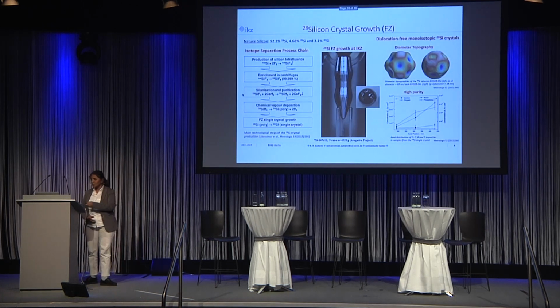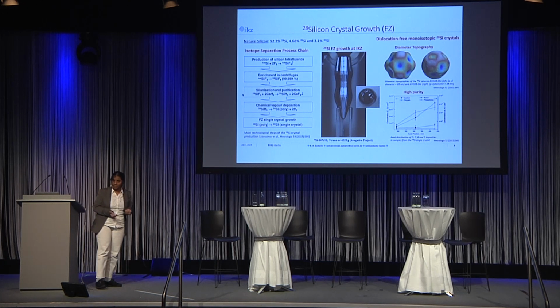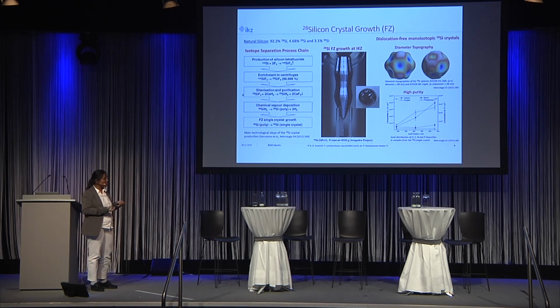And now I would like to come back to what we are doing at our institute to supply this material: we are growing bulk crystals of silicon and silicon-28 using the floating zone technique. This is one of the crystals, a 4-inch diameter isotopically pure silicon-28 single crystal, which has been grown for the Avogadro project, a historical project of our institute to prepare a 1 kilogram ball to redefine the kilogram unit. So this is how the history of isotopic material started in our institute, and still we are working on this material for applications in quantum computing.